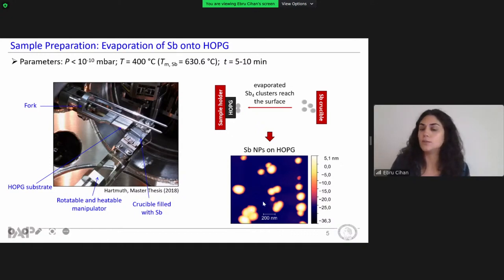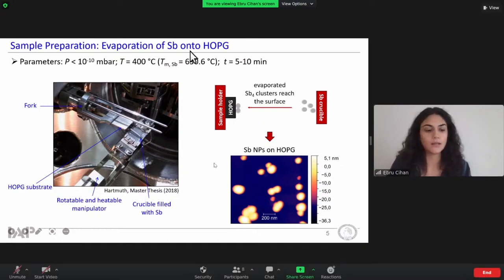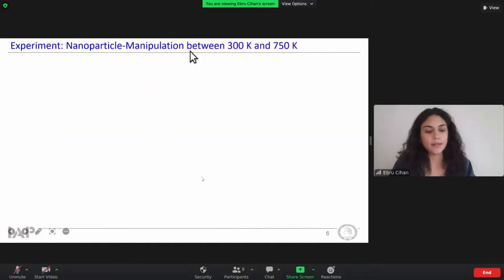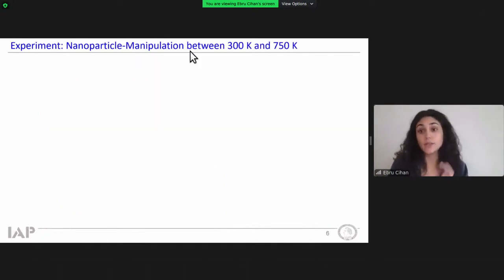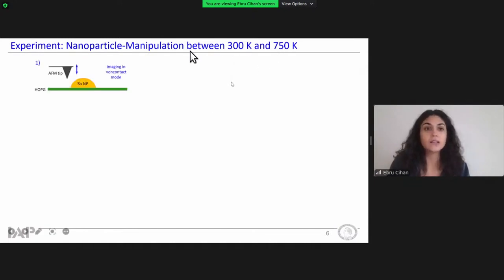As you see, these are the antimony nanoparticles on graphite, a general overview after deposition. For further manipulation experiments, we transfer the sample, as I said before, to the atomic force microscope. And then the nanoparticles were laterally manipulated on graphite at different temperatures between 300 Kelvin and 750 Kelvin. All nanomanipulation experiments were performed as a three-step process.